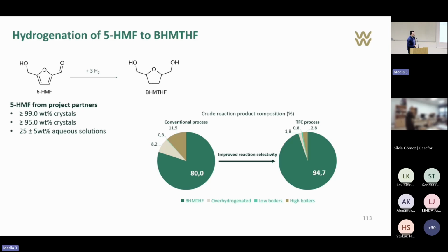So then we moved on to 5-HMF and tried to convert it to BHMTHF using the same technology that we developed for methyl THF and THFA. We got some 5-HMF from our project partners in 3 different grades and tried to convert these different grades. There were some differences, but in a nutshell, we compared the hydrogenation of 5-HMF using a conventional hydrogenation process, and then compared it to the TFC developed process just to see if it would perform better.